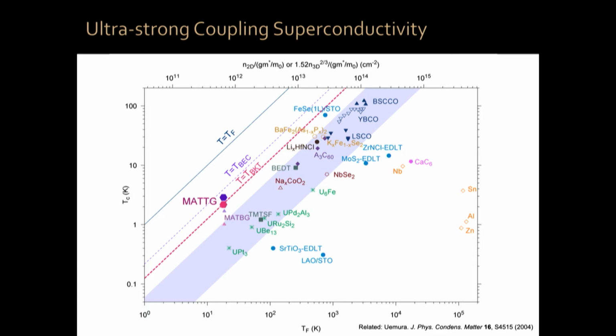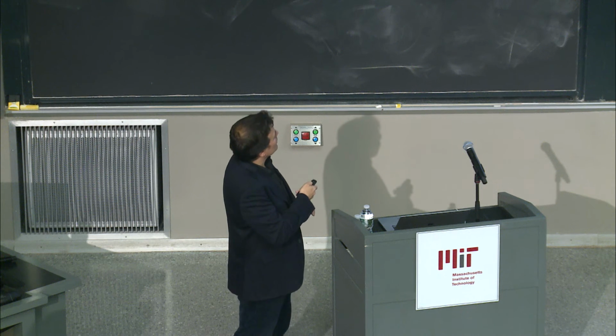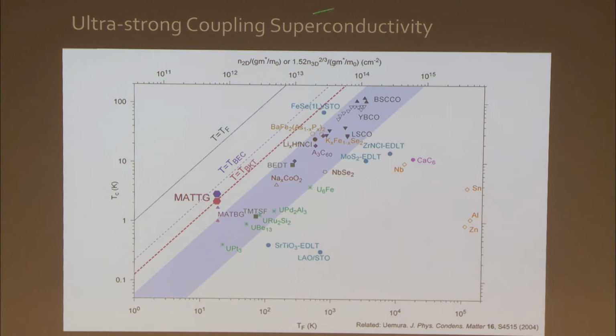I mean the following. Usually when physicists compare superconductors, what we do is we compare the critical temperature versus the Fermi temperature, or the density of electrons, okay? For example, conventional superconductors, okay, those that are understood with the weak coupling theory of BCS superconductivity, are typically near this corner. For example, aluminum. Aluminum has a TC of 1 Kelvin. It has a Fermi temperature of 100,000 Kelvin. It has a gigantic density of electrons, okay? The more you go in this direction, towards this purple band, the more exotic your superconductivity becomes, okay? And in fact, in this purple band are all of the unconventional superconductors, the cuprates, the pnictides, the organics, the heavy fermions, they're all here. They have a relatively high critical temperature with a relatively low density of electrons, okay?